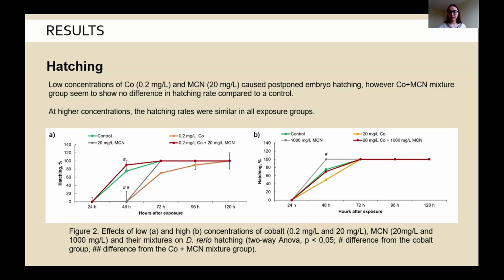On the right, you can see the image of higher concentrations, and here the hatching rates were similar in all exposure groups. The only statistical difference was in the 1000 milligram per liter MCN group, which was statistically different from the cobalt group, but not statistically different from the control.